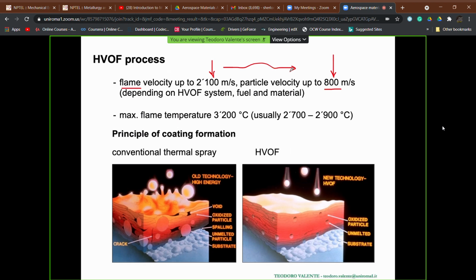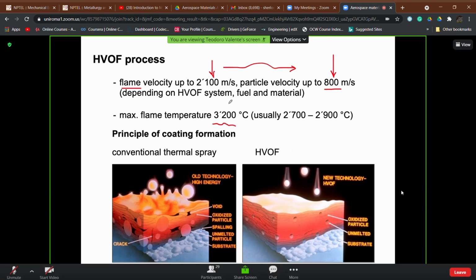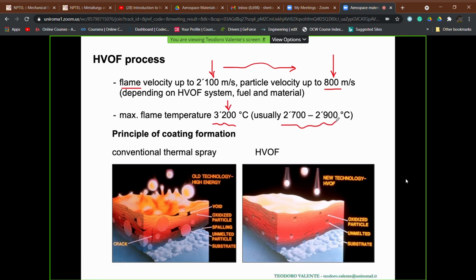So very fast process. The maximum flame temperature, depending on the fuel which is used, is around 3000 Celsius, even though usually it is a little bit lower than 3000 Celsius, but not so much. And so again, remember that this process is not the most suitable to fabricate coatings starting from high melting point materials, like, for example, ceramic materials, oxide-based ceramic materials, because the melting degree obtained is not sufficient.